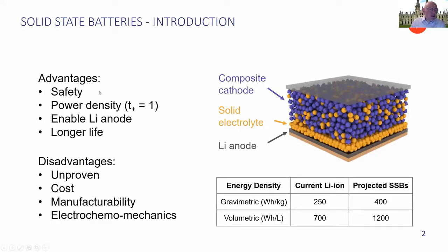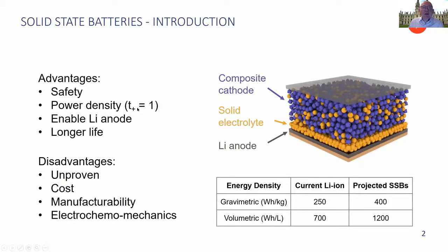Here are some of the advantages. One advantage is safety because we're not using flammable organic liquid electrolytes. There's also a potential advantage in power density: in liquids both cations and anions move, leading to concentration polarization especially in the pores of the cathode, whereas in a solid electrolyte only lithium ions move, so potentially you could have faster charge and discharge rates. It also enables the use of lithium metal anodes and could lead to longer calendar and cycle life.